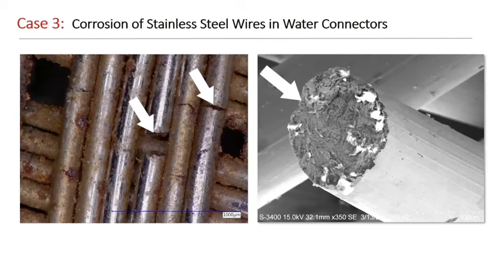Here are some images that I took in the lab. The one on the right is with a scanning electron microscope. As you can see, this one is at about 350 times magnification, but obviously these microscopes can easily go to 10,000 and 100,000 times to look for very small features that can be the root cause of the failure. On the picture on the left, I'm showing a visual microscope of those braided wires, and as you can see, there are some cracks that are developing. I'm showing them with the arrows there.